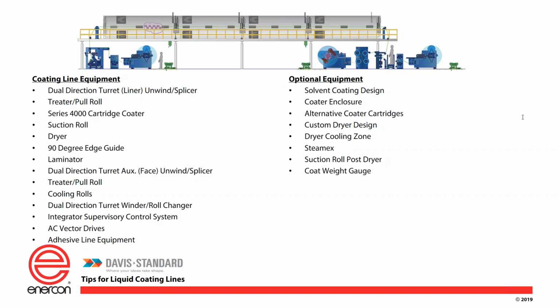So as you exit, you use a guide. And here we're showing you a 90-degree edge guide. So we get the web back to the center so we know exactly where it is, and we bring it down to the laminator section, which now to the right end, we show you another turret unwind. Here we have a 2-side treater pull roll. So I treat one side for improved laminations. I can treat the opposite side for printing or whatever my next step's going to be into that laminator. And we will take the web guide upstairs that senses the web and match it to the web that's coming in off this unwind. It's called hunt and chase, so that they're laminated straight to one another.